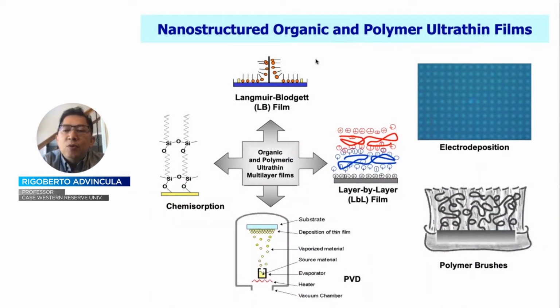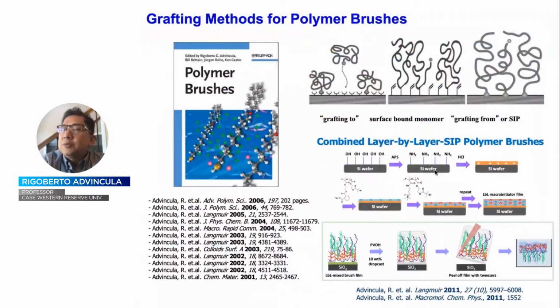So in my work as a professor, we have also worked on a number of what we call ultra thin film coatings. These are nanostructured layers or coatings that can be controlled to less than a nanometer in thickness. This can be done by chemical adsorption or physical adsorption, divided into different types of coatings by layering, grafting of polymer brushes through chemical and polymer modification, or the adsorption of electrolytes, electrodeposition, and so on. In fact, we specialize in a technique called polymer grafting, or polymer brushes, where we combine the chemistry of doing polymerization on surfaces, whether it's carbon steel, plastics, or silicon wafer, and the ability to control the brush density of those grafted polymers, which can have many advantages in terms of the ability to control diffusion and corrosion.